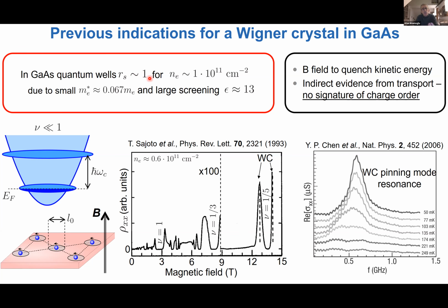But since rs is on the order of 1, at zero field there is no way of seeing a Wigner crystal. So what the community did is to apply large magnetic fields to quench kinetic energy, and then look at low filling factors of the lowest Landau level. In this case, the theory predicted that the system would undergo a Wigner crystal transition for filling factors less than about 1/5. And indeed, transport measurements, in this case longitudinal resistance, show that beyond the 1/5 state, the resistance remained very high, and this is consistent with the explanation.